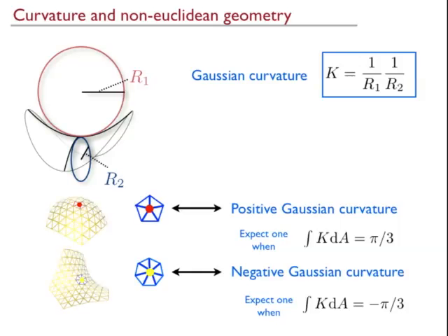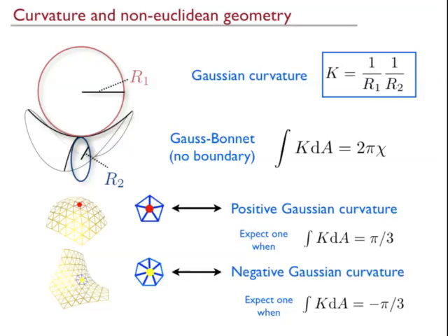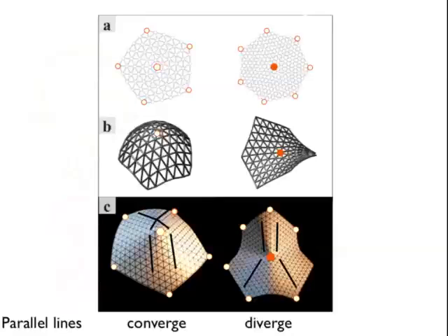Okay, so this is what they'll look like on a curved surface. This is a 5, this is a 7. They contribute pi/3 of Gaussian curvature. There's a theorem, which is called the Gauss-Bonnet theorem. The Gauss-Bonnet theorem says the integral of the curvature is an invariant. It's 2 pi times the Euler characteristic. So for a sphere, I have to end up with 4 pi worth of defects. And if this guy gives me pi/3, that again gives me 12 of them. This is another way of counting it.